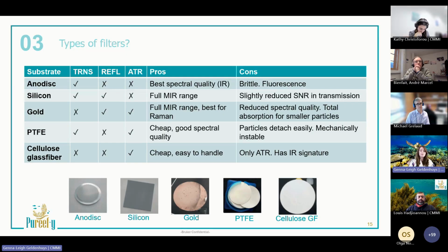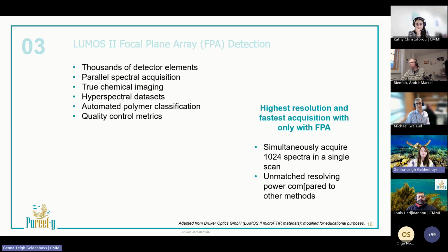and are easily automated. And for this, the Anodisc filters, like the aluminum oxide filters, are currently considered the gold standard. They are IR transparent, they cover most of the relevant spectral range, and they capture particles down to sub-micron sizes. They also provide excellent visual contrast. And they're also ideally suited to both FTIR imaging and single point analysis in transmission measurement modes. And if you want to do something like Raman spectra complementary with FTIR spectra, something like a gold filter will be the choice there.